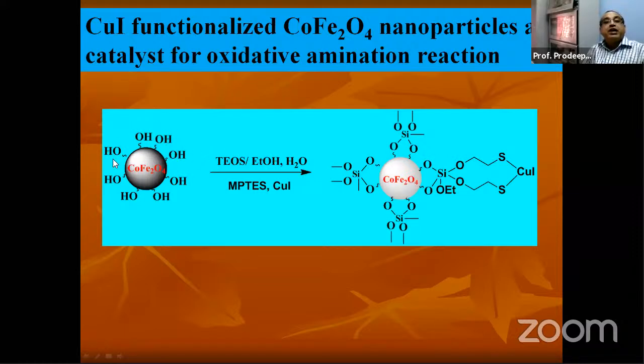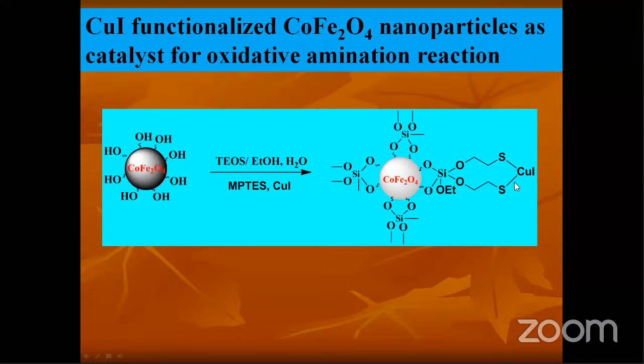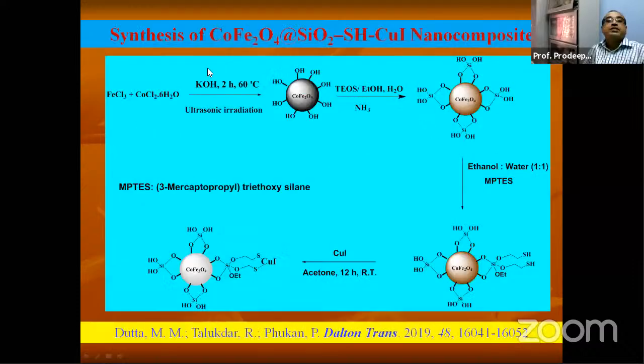Then what happens? We have used again cobalt ferrite surface functionalized particles to hook cuprous iodide. You can see here, these are the methods. First we made this cobalt ferrite nanoparticle. Then we coated the surface with silica. Then we have used MPTES, so surface functionalization took place. Then simple cuprous iodide we have added because there is sulfur there. So cuprous iodide got hooked onto the surface of the nanoparticle. So this is the nanoparticle with cuprous iodide on the surface.